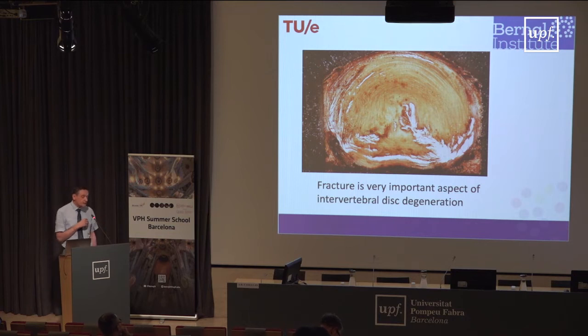Now, a second theme I would like to talk to you about is fracture. And fracture is a phenomenon which is extremely relevant to disc degeneration, because most of disc degeneration is associated with fracture. And fracture means that very locally at crack tips, there are very large strains, even in relatively stiffer environments such as disc or cartilage. And the strains are large, and there also we expect local mass balance violation. Now, the disc is known to be cracking or tearing as it degenerates, and usually this tearing is not very much associated with loading. It's actually intrinsically associated with aging, swelling, loss of fixed charge density because of the degeneration.